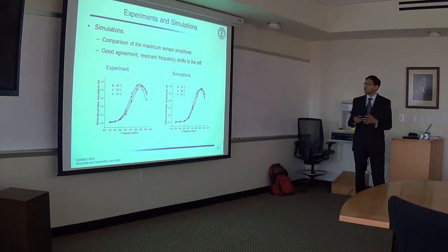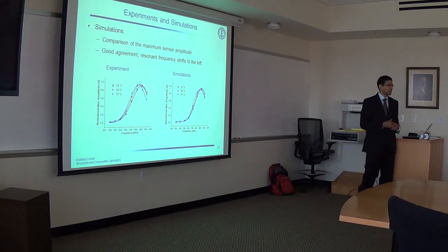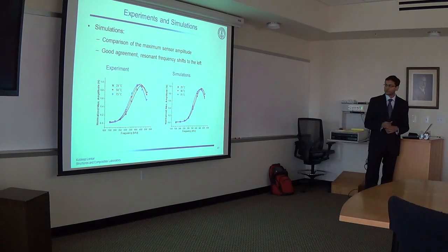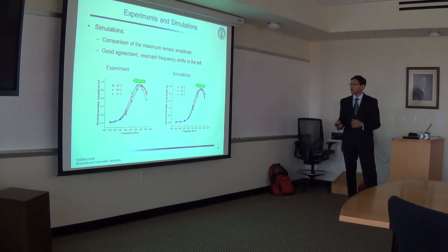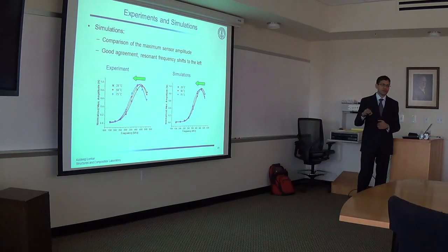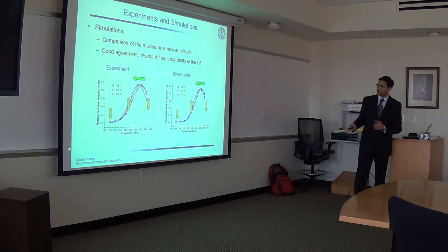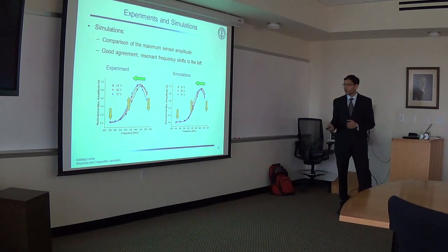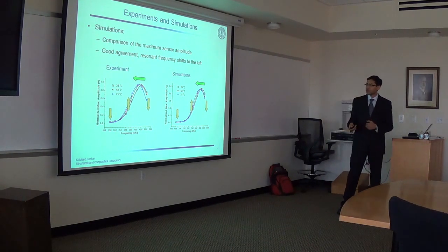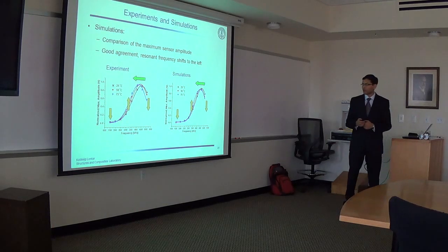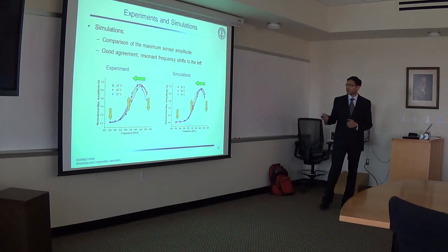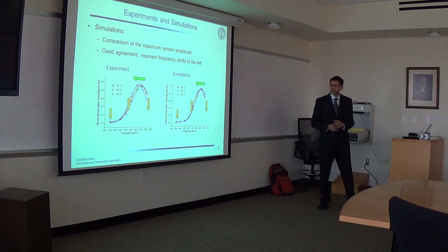As we can see, the simulated results are in very good agreement with the experimental results. As we increase the temperature, the resonant frequency shifts to the left, and we see that the amplitude of the sensor signal decreases at low frequencies, and in this frequency range, it increases with temperature, and in the frequency range that's higher than the resonant frequency, it decreases as we increase the temperature. And we can capture this effect very accurately in the simulations.